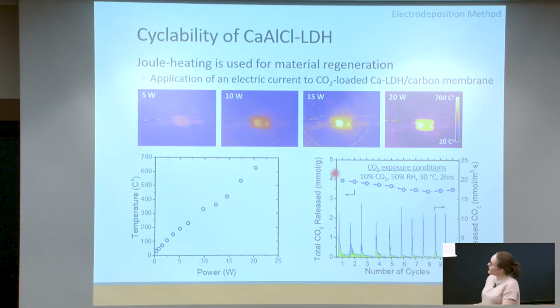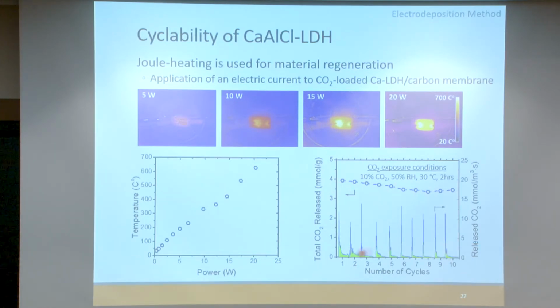You do get a slight decrease in the amount that's captured as a function of the number of capture cycles. This is very typical of sorbents, whereby some changes occur that effectively decrease your capture capacity to some degree. But here, the decrease is on the order of about 15%, so it's not too bad. We haven't dropped by a third, for example, after 10 cycles.